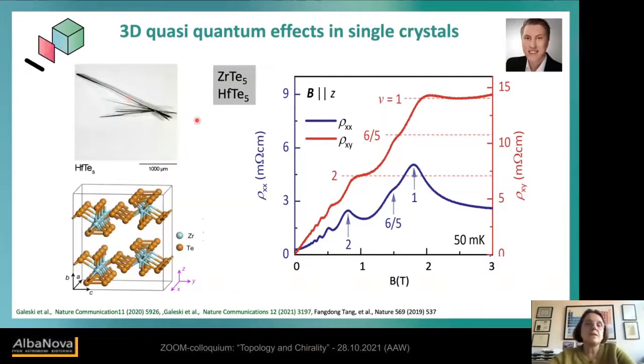And what was surprising also for me, what was recently discovered, if you saw my slide, is that zirconium telluride 5 is a very good topological material. Many interesting properties were discovered in this compound. But even if you simply look at the intrinsic properties of this compound, it was found that even in the three-dimensional crystal, not a complex two-dimensional electron gas, but the crystal is a little bit quasi two-dimensional. If you see here, you could imagine these kinds of layers. You see this quantum Hall effect. So you see exactly the plateaus which Klaus von Klitzing saw when he did his measurement on the two-dimensional electron gas. And on top, even in a single crystal, nothing else but a high quality single crystal, you can even see a fractional quantum Hall effect. So there's a nice connection between topology and the quantum Hall effect, which is realized here in the single crystal.